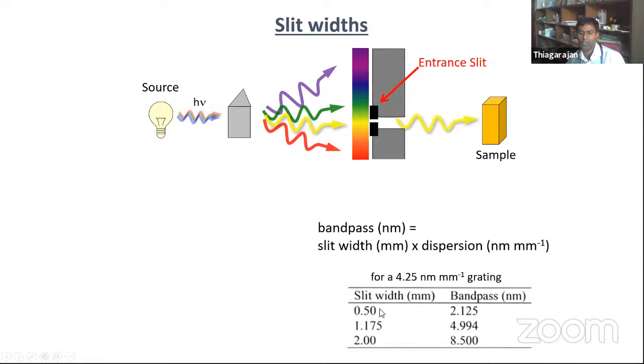You see the slit width is 0.5 millimeter, the band pass is 2.125. Thus, when we increase the slit width, the band pass also increases. So if you are more keen on the wavelength, then you should use the minimum slit width. If you are not keen on the wavelength maximum or spectral resolution, you can use the higher slit width.